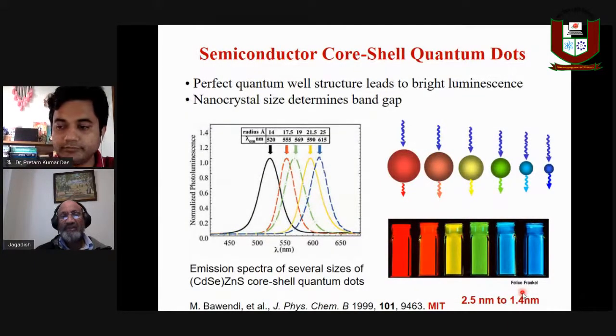So here is an example of the case where these are the results of Professor Moungi Bawendi. You can see that these results are more than 20 years old now. They've been able to show this by changing the dimensions of these cadmium selenide quantum dots coated with zinc sulfide. Because cadmium is toxic, they coat with the zinc sulfide, and it also improves the performance of these quantum dots.